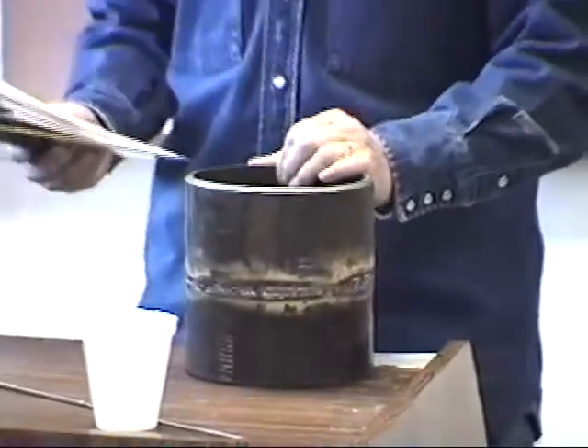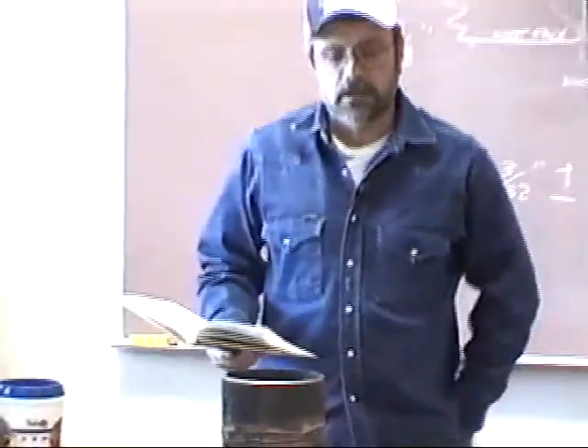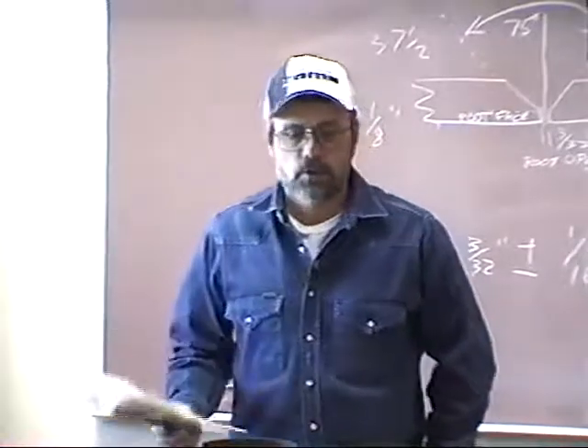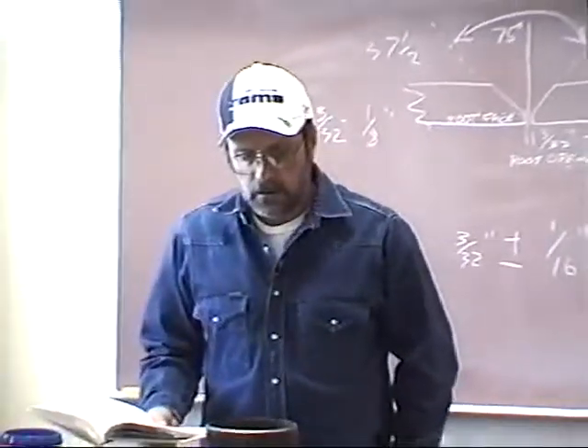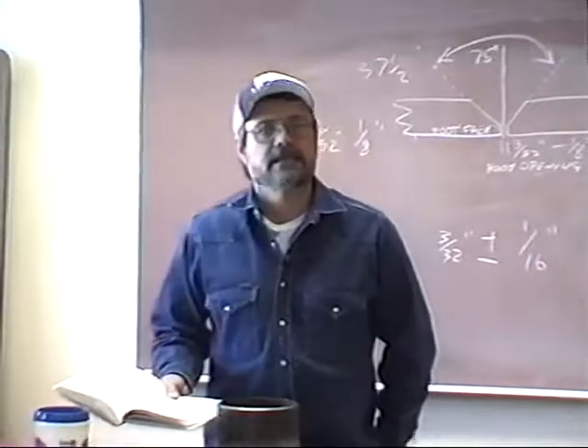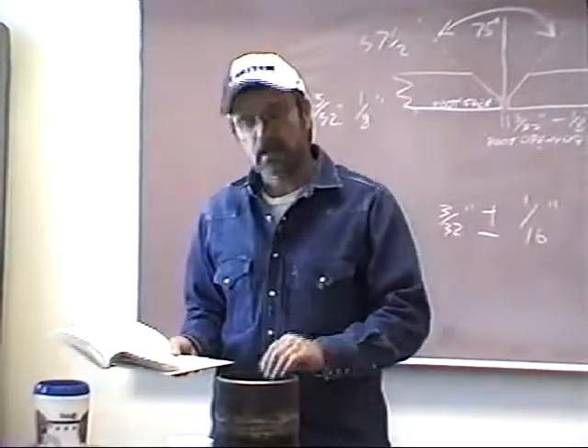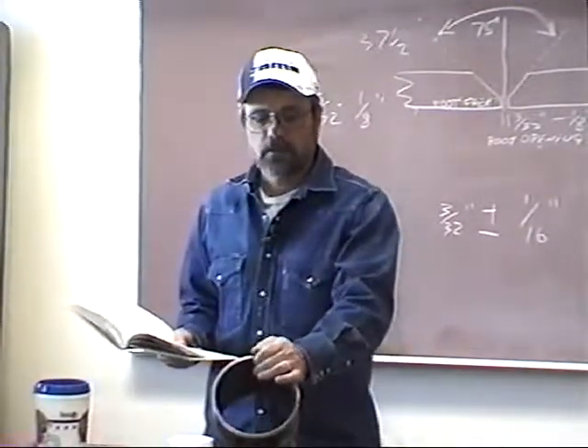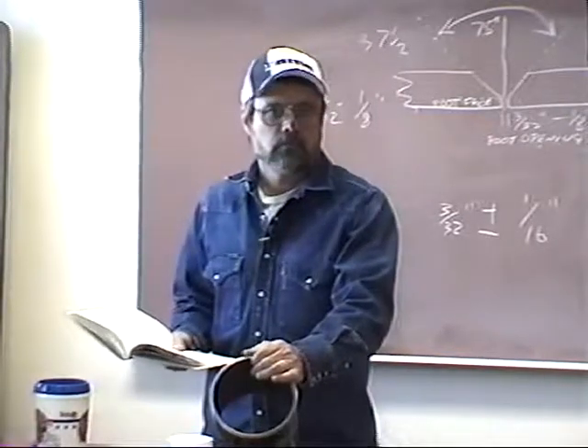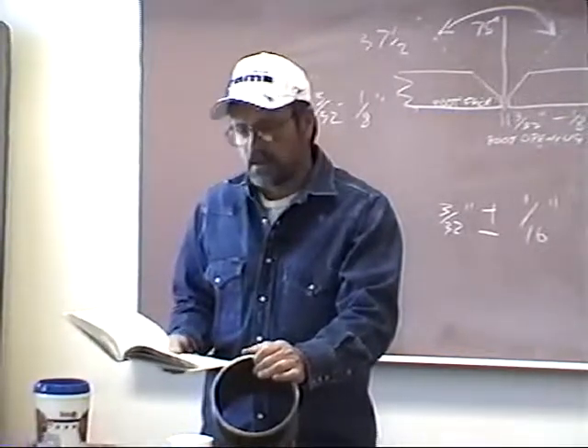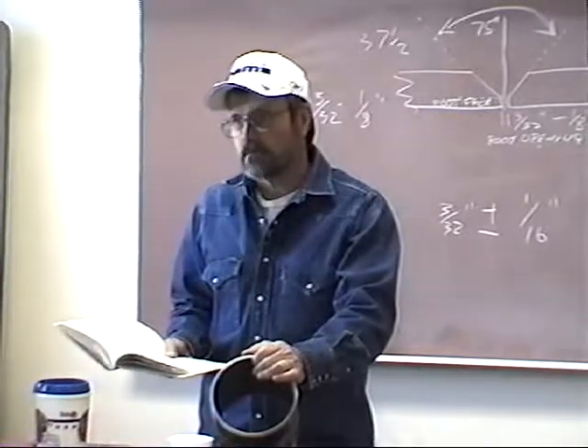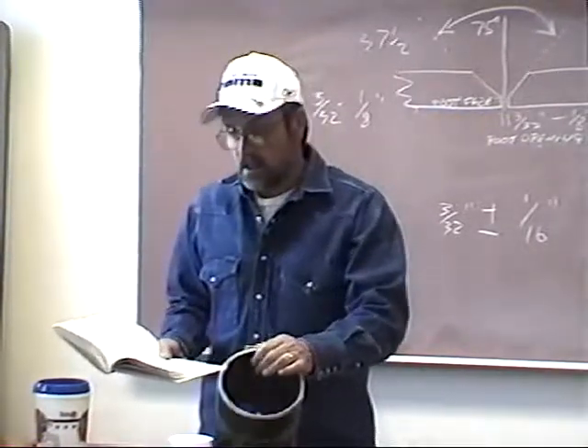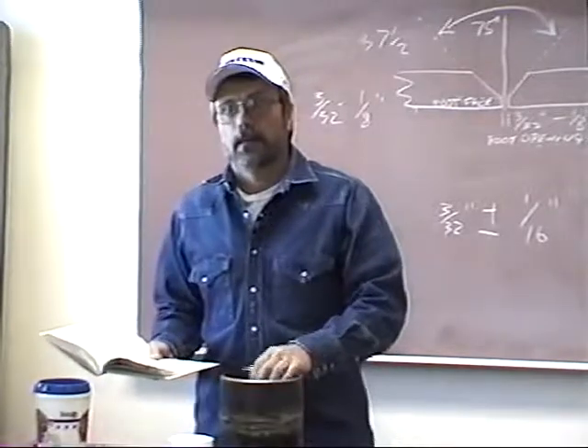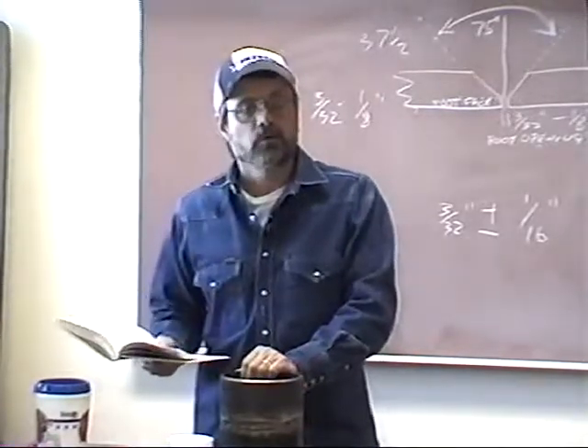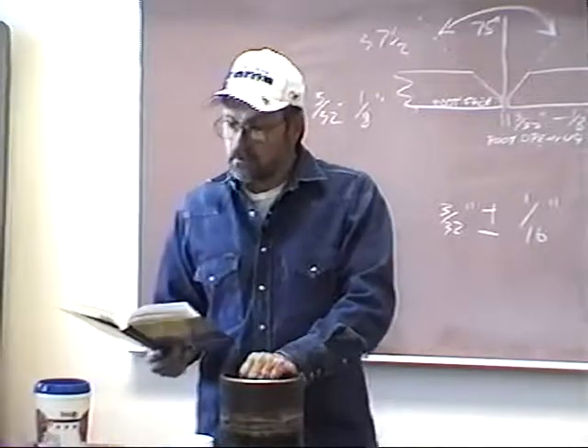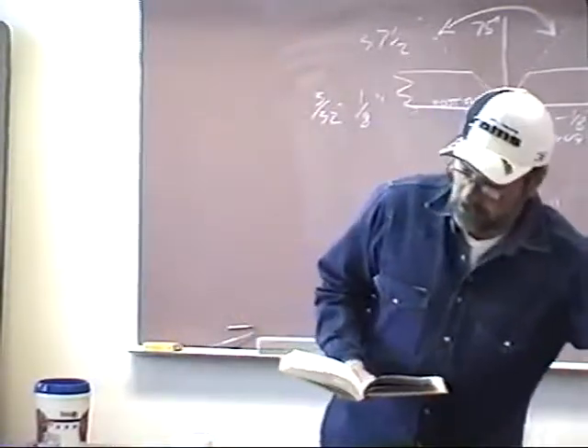It's important to remember that when you take a welding test, usually under ASME, you're qualified for twice the thickness of the pipe that you actually weld. If you were to take an ASME test on this pipe, you would be qualified to weld almost 5/8 of an inch thick. If it was Schedule 80, you'd be qualified to weld over 3/4 of an inch thick. However, some codes will only allow you to weld to the actual thickness of the coupon that you took your test to. Depends on the welding test.